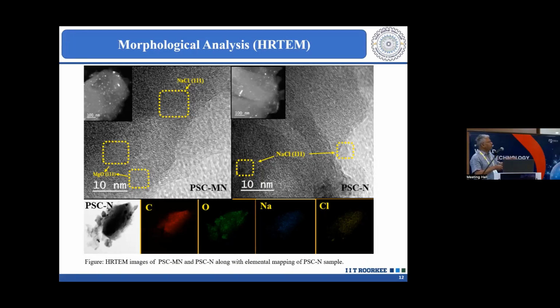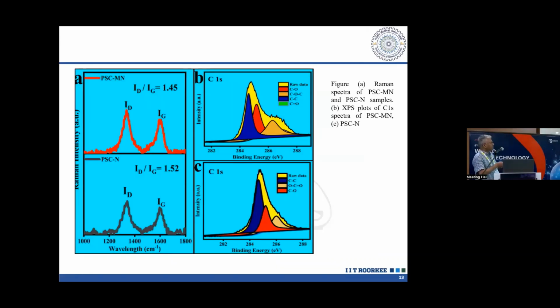So in order to tune and control the sodium storage mechanism, this shows what the elemental distribution is. Now we have performed the Raman spectroscopy just to see the disordered peak versus the graphitic peak, and then the ratio of the two materials, one material is this, the second material is that. So for the two different materials, there is a slight difference in the ID by IG ratio.